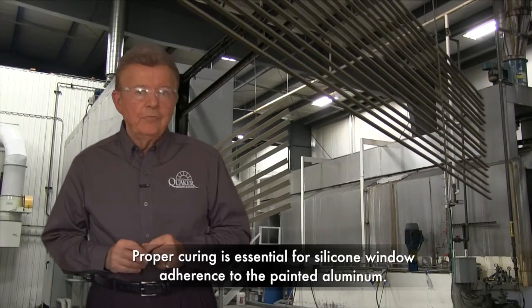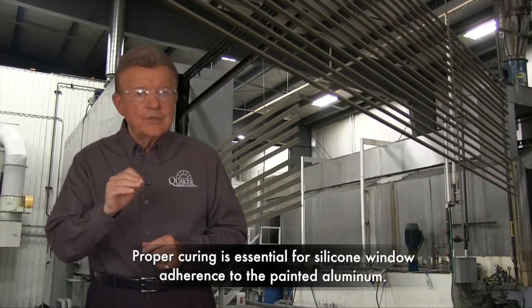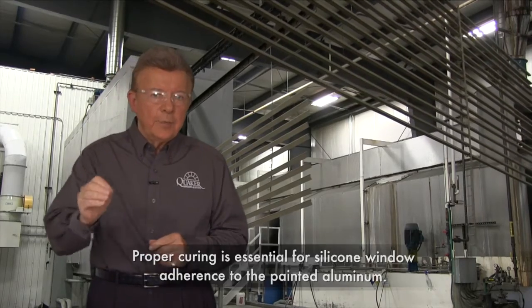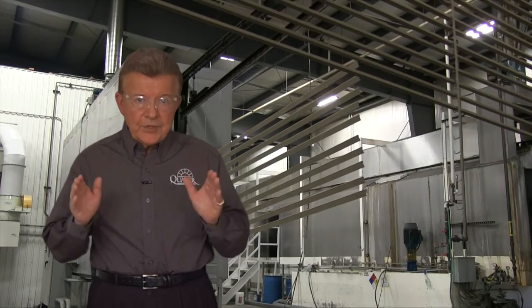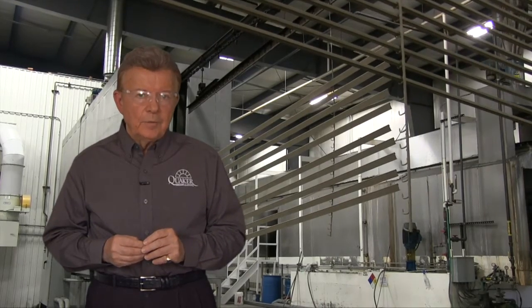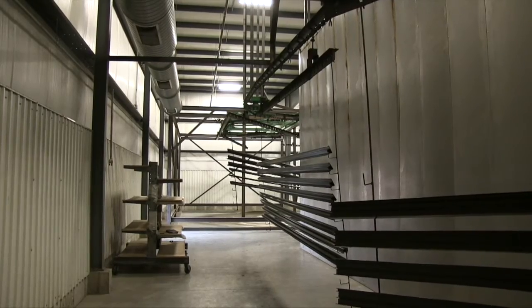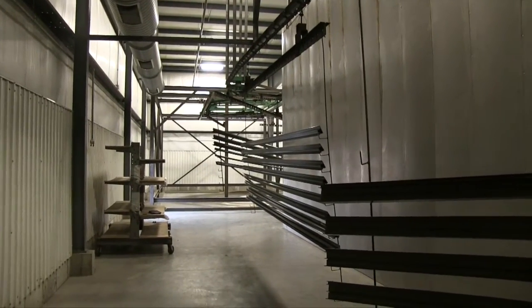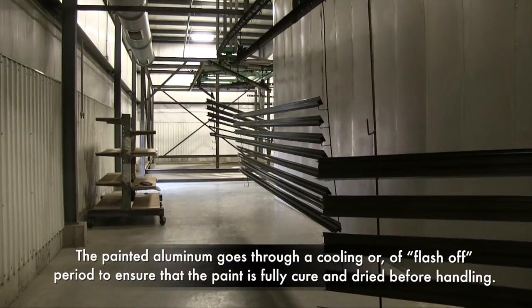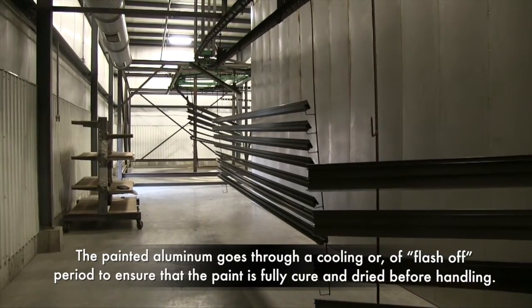Before reaching production, floor quality control will perform a series of pull tests on each run of painted aluminum before it's released to a production line to ensure that the paint has achieved optimal curing and that applied silicone will properly maintain adhesion. This again is critical to the long-lasting watertight windows or doors Quaker manufactures. Once the baking process is complete, the painted aluminum goes through a cooling or flash-off period to ensure that the paint is fully cured and dried before handling. This takes about 20 minutes depending on the size of the rail.